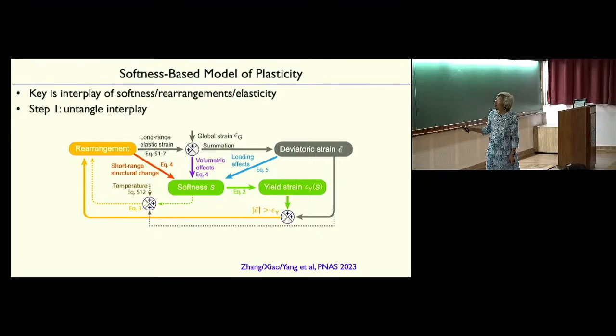Then I have this total strain, which comes from loading the system, from shearing it, as well as from these rearrangements, and I can compare that. The softness gives me a yield stress or yield strain, and if my strain exceeds that yield strain, bam, I can have a rearrangement. So it's a complicated diagram, but that's the physics that I'm trying to capture: this interplay between softness and plasticity, rearrangements, and elasticity.